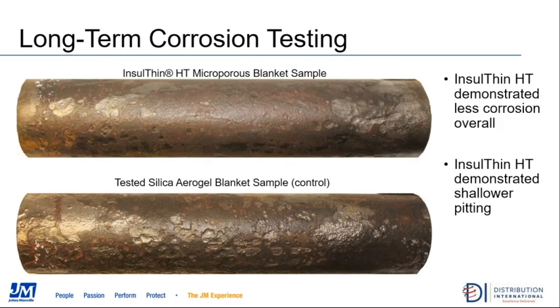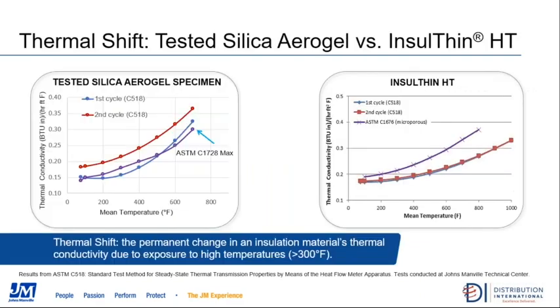This is the same kind of pipes. We did the same kind of long-term testing. Again, this was a 6-month test over 600 cycles, and much less corrosion overall compared to silica aerogel, and significantly less pitting. And again, pitting is the key, the depth of the wall loss. And again, if you want to see more on this, we've got several presentation modules that our sales reps or technical managers could come in and give you over a lunch and learn that can get into greater detail on all of this CUI stuff. But this is just a tease right here.